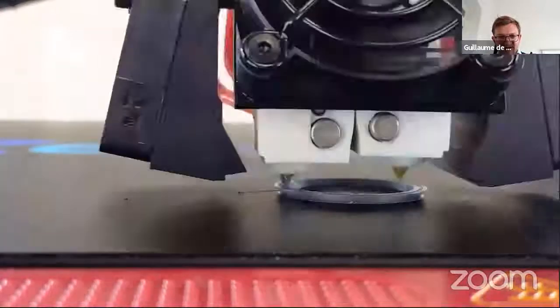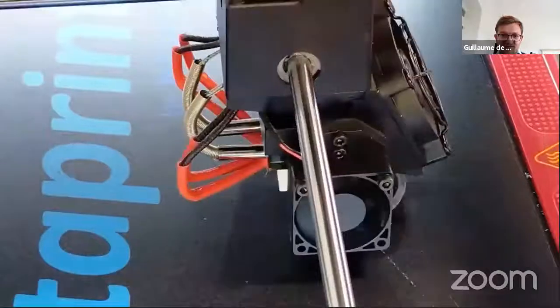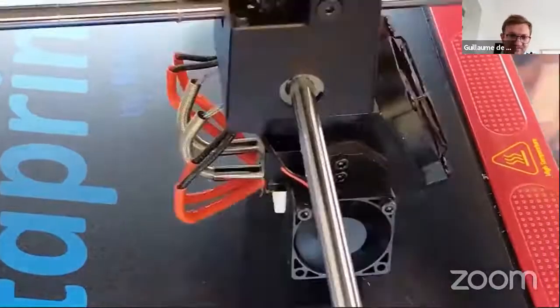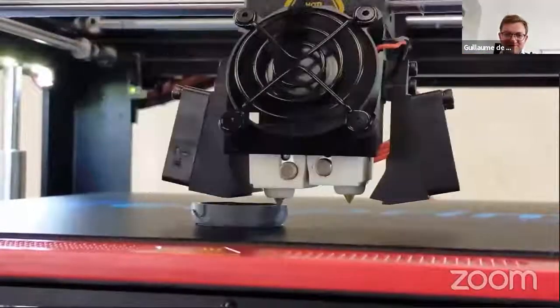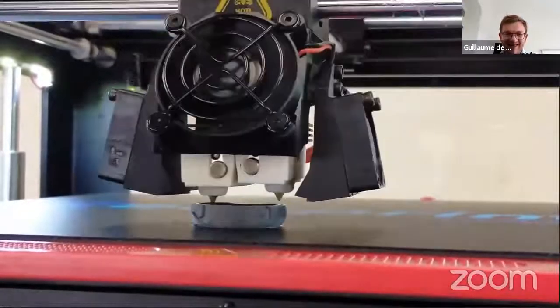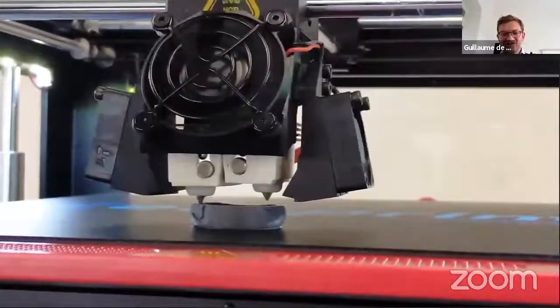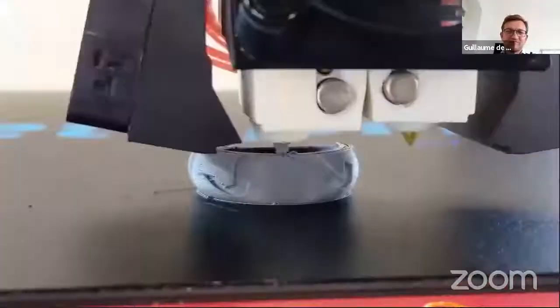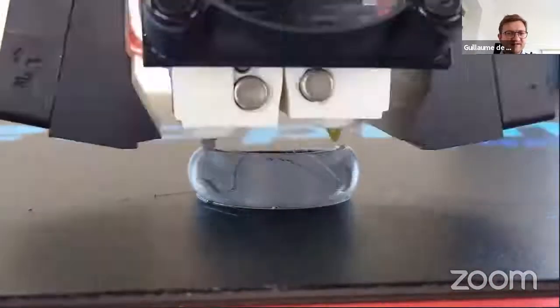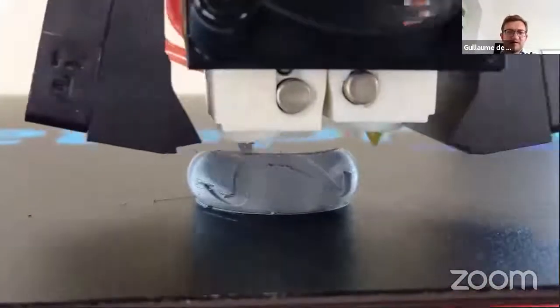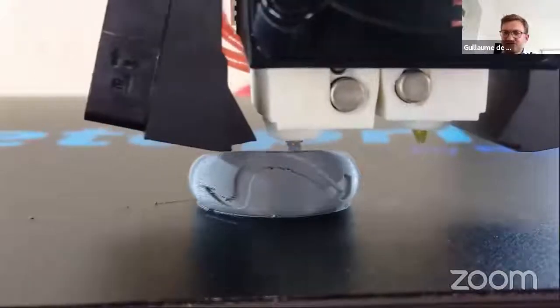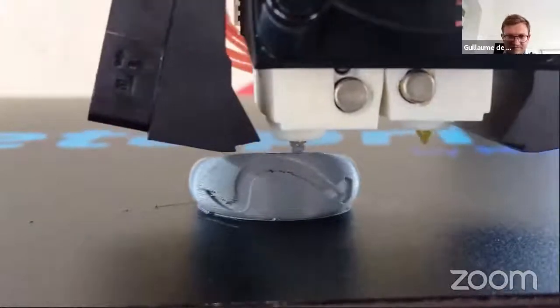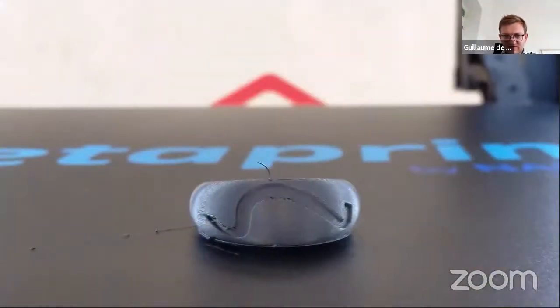Maybe you can see it, but we are printing with an infill, which means that the part is not fully dense. We can see that a bit if you have a trained eye, and you'll see the parts growing progressively. A part of that size takes typically, I don't know, something like 40 minutes to print for a ring, and that's it.